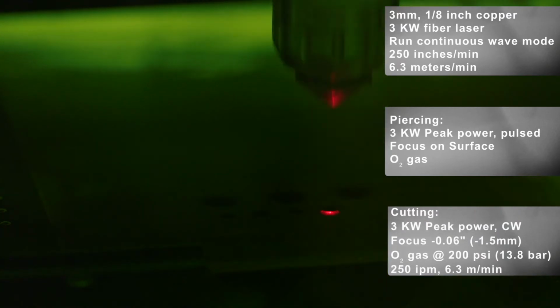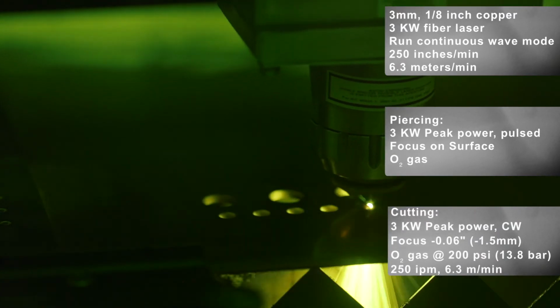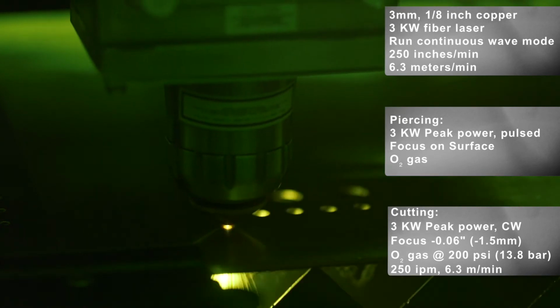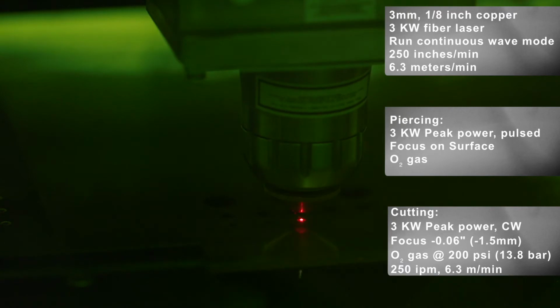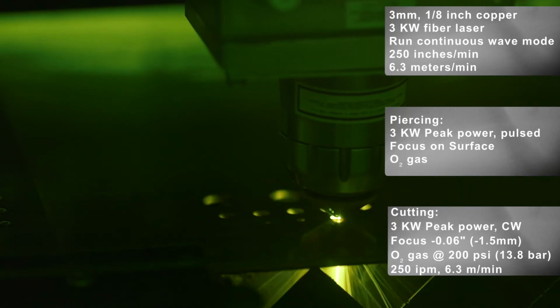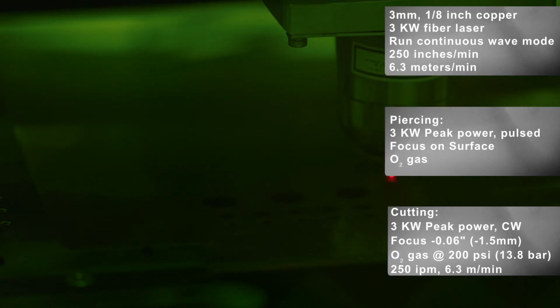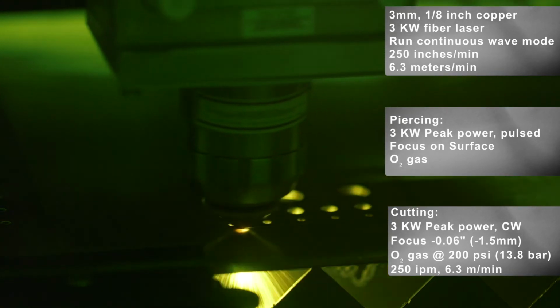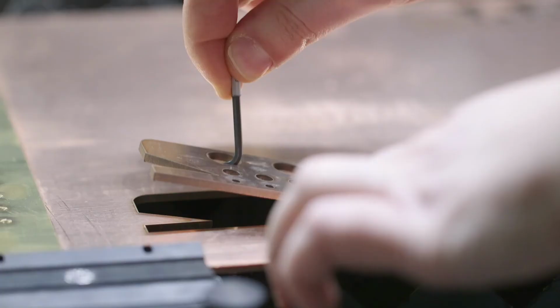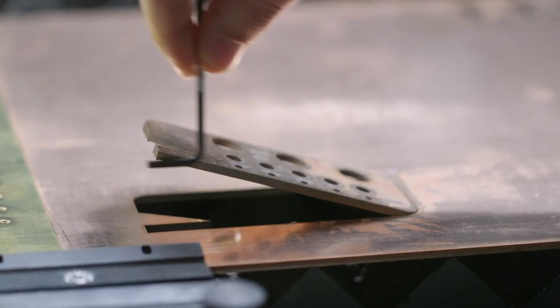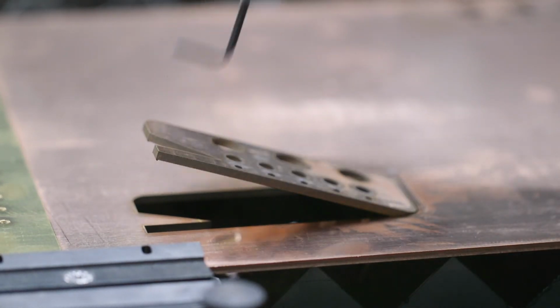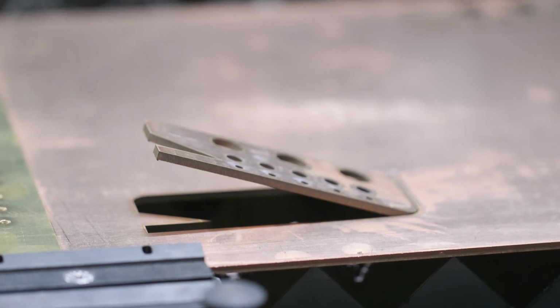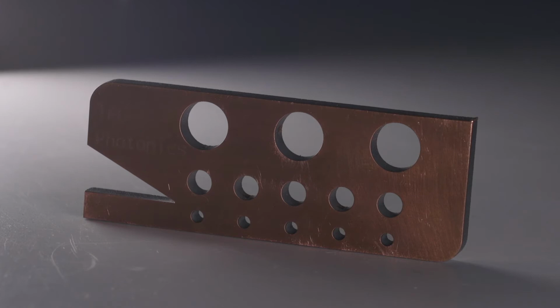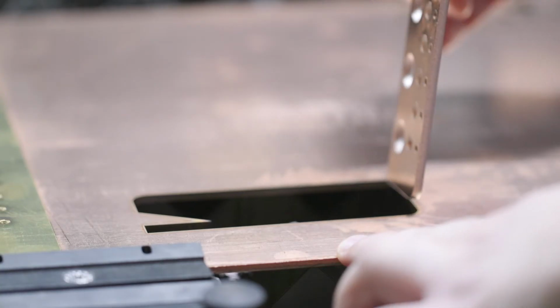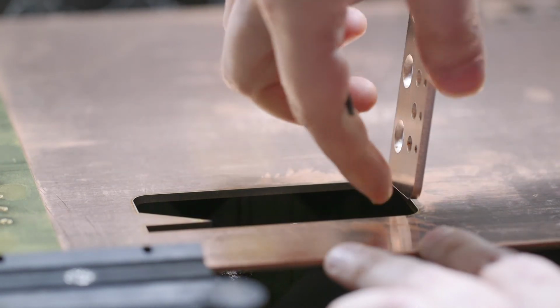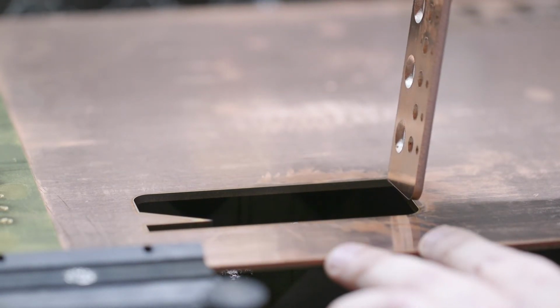For the cutting stage, I focus down about 0.06 inches below the surface of the material, and the laser is in the continuous wave mode, or CW mode, and running at 250 inches per minute, or about 6.3 meters per minute. So you see, there is a little bit of dark edge because of using oxygen as the gas, but that's normal in cutting copper with high pressure oxygen. And there shouldn't be a significant dross that you can't remove with the finger.